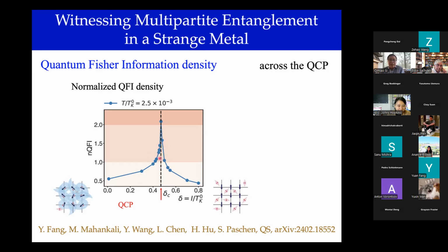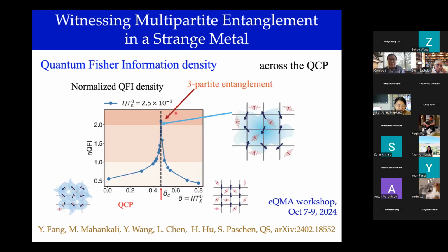entangled or not. Here it's a many-body system, and this quantum Fisher information turns out to be peaked in the quantum critical fan. This is still a finite temperature calculation, but it's peaked very close to the quantum critical point. And in fact, by using the bounds of the entanglement content through this normalization, there's a multipartite entanglement that happens within the quantum critical fan, and one could qualitatively say that the Kondo screened phase has the entanglement between local moment spins and the conduction electron spins. One actually needs some other entanglement measure to detect that. And the Kondo destroyed side has the picture of the two standing alone. This multipartite entanglement suggests that you have these blobs.